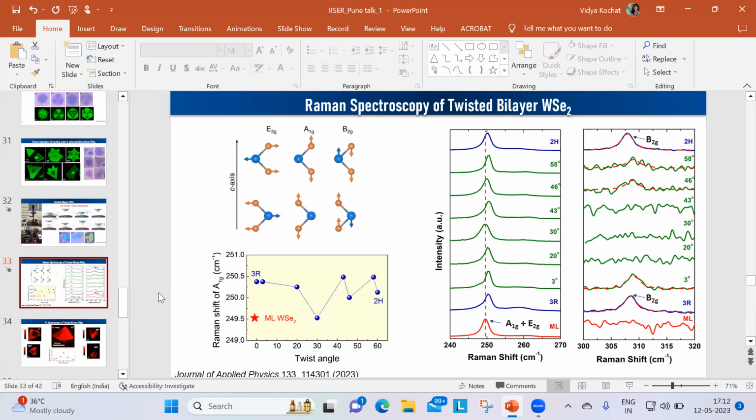Yes. There are band structure calculations from which you can see where the C exciton should be. And this energy varies as you change the temperature, so you might lose the resonant condition also. At room temperature for this system, this is a resonant condition which is giving rise to this kind of contrast difference.